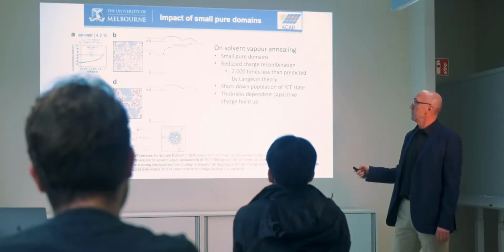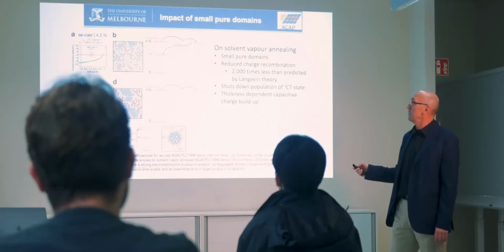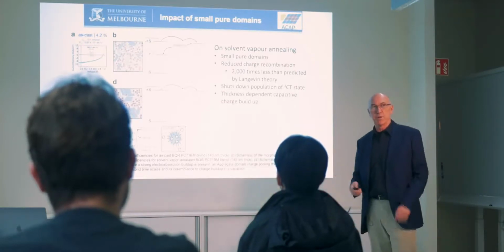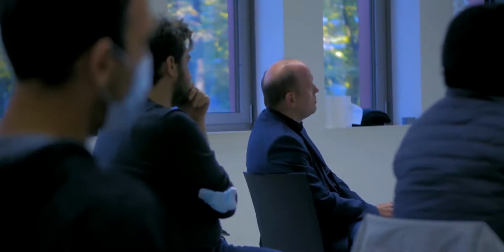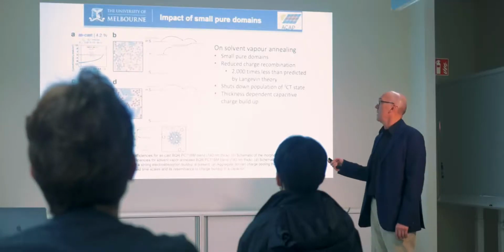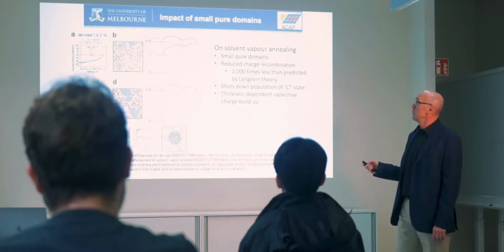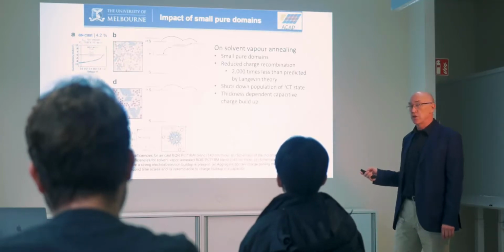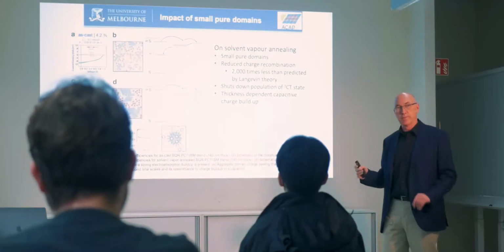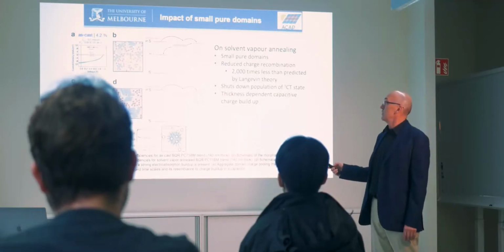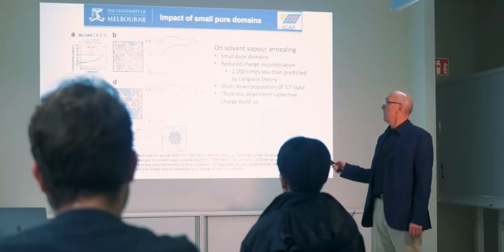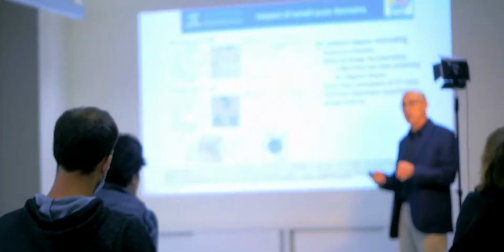And so we excite it, and then we have charge separation, and then we generate these two polarons. Just positive and negative charges, depending on what field you come from, how you refer to them. They can be positive and negative polarons, they can be radical cations, radical anions, or they can just be charges. Once we get here, we also can recombine these charges to get what's called a charge transfer state. And if we generate the charge transfer state immediately, it'll be a singlet. If we recombine charges, it can also be a triplet. That just is talking about the spin configuration of these. The electrons are either both up in a triplet or up and down in a singlet.